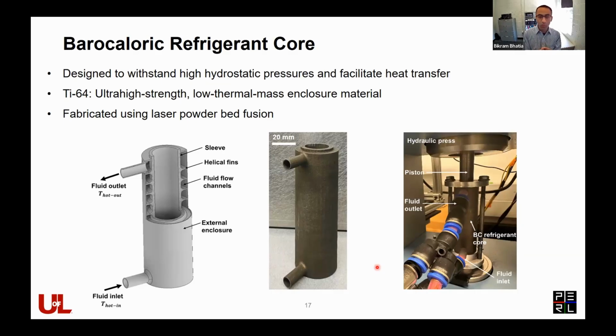So we really focused on the wall thickness of this heat exchanger, because we don't want the Ti-64 wall thickness to be too large, because then it impedes heat transfer, but also we didn't want it to be too thin, because then it won't be able to withstand the pressure. So we did calculate the hoop stress and determined that around 2 millimeter thick wall is good enough with a certain factor of safety for our experiments to design this heat exchanger